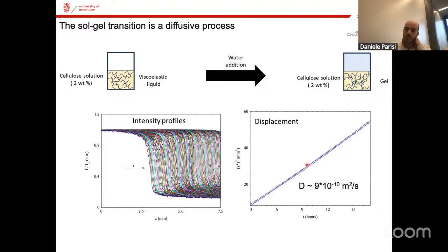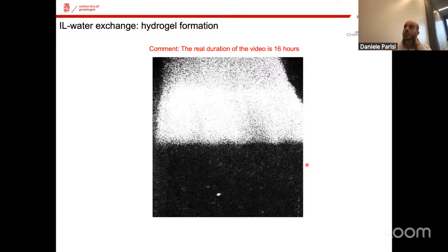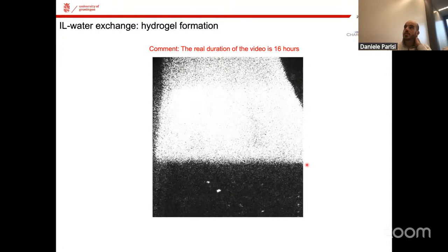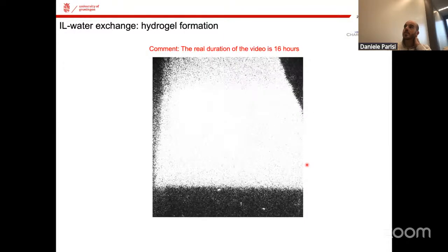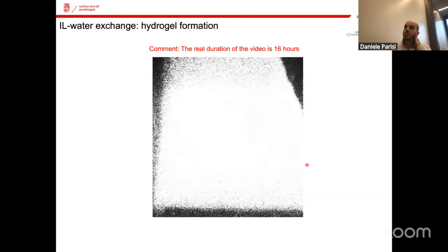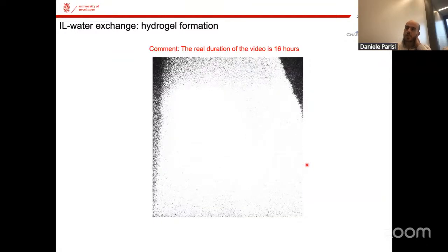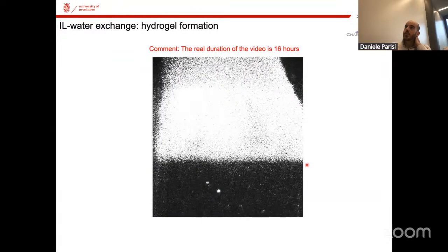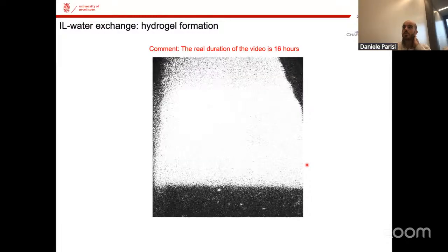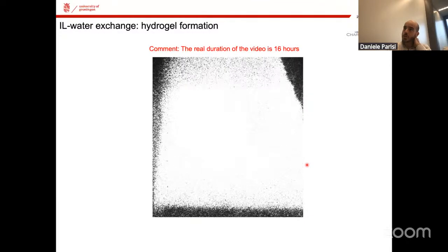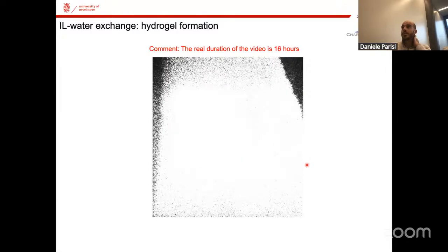So it looks like this gelation front evolves linearly, it's diffusive, and it moves like a sort of plug flow, as you can see from this video here. This is just a sped up video because it took us 16 hours to record it. But let me show you again, perhaps. So the gelation front moves really like a sort of plug flow. So it's quite homogeneous, with a very linear function of position and time. So it's a diffusive way of gelation.